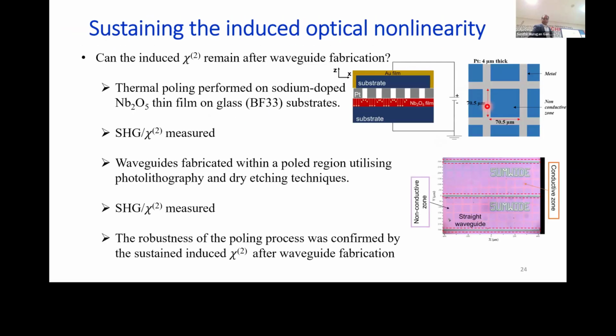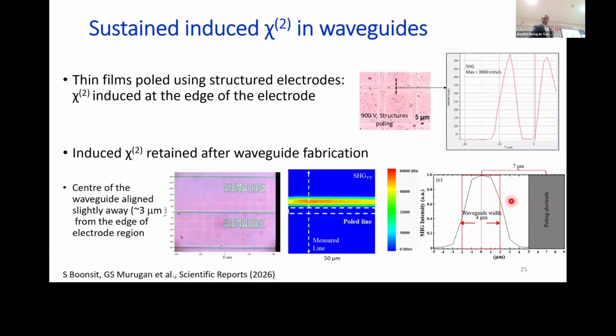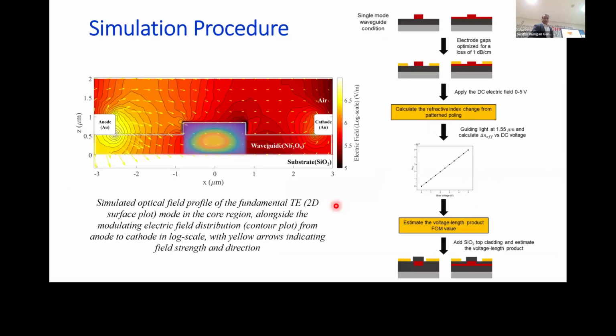So we applied this, and we have also shown that after getting the Chi2 established, after the waveguide has been fabricated, the Chi2 is still available without any decay. So what we are showing here is the sustained induced Chi2 in this material, which was retained after the fabrication of waveguides. That means now our waveguide platform is available with Chi2 property, and therefore we can fabricate electro-optic waveguides.